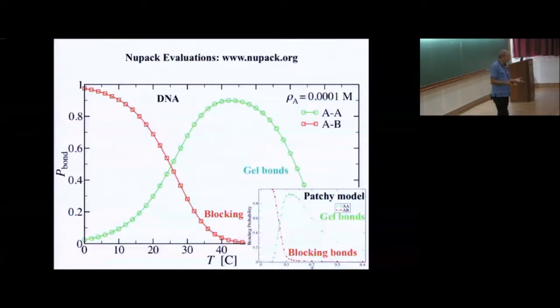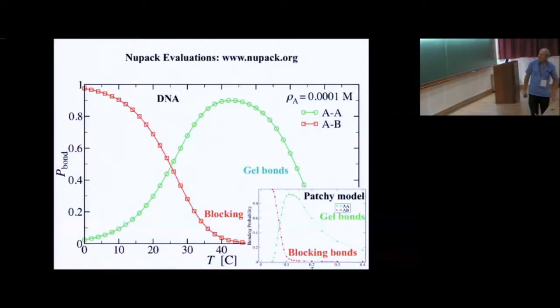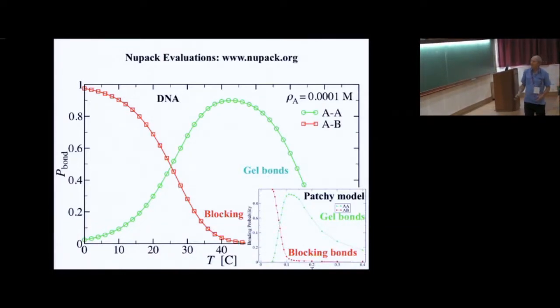Now you use this theoretical software that has been developed for DNA. You can type in the sequences, and it tells you the temperature where you expect to have these sequences to bind. And so you can do the theoretical calculation, and you see that these blue-blue bonds behave like that, as we wanted, and the blocking bonds attach in this way here.